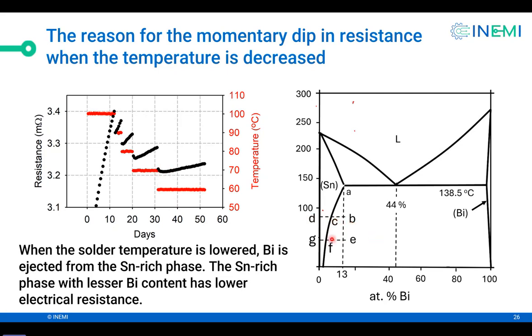Now to go from composition C to composition F, that's a diffusion phenomenon. The bismuth has to diffuse out of the tin-rich phase into the bismuth-rich phase. So diffusion takes time. You can see over here, it took about 3-4 days to take the dip and go up. But also notice that at this high temperature, there was no dip. At 70 degrees, the dip lasted longer, 60 even longer. That's because the diffusion process is slower at lower temperatures, so the dip takes longer.